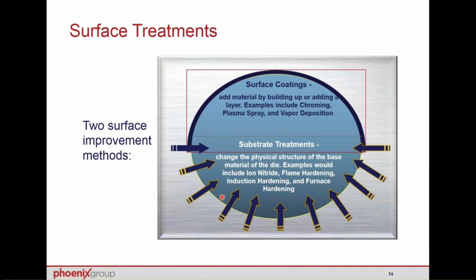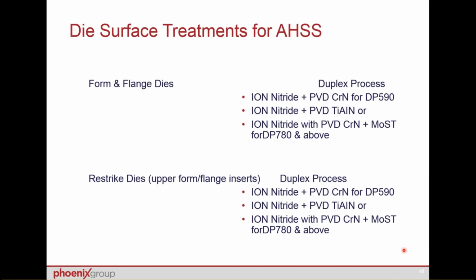With the ion nitriding, because you have to slowly bring it up to temperature, hold it for a period of time in the oven to allow the penetration of the nitrogen ions, and then slowly cool it back down so we don't end up with thermal fracturing or warping, it might be a 3 or 4 day process in order to get a die back. Also, you have their equipment tied up for a longer period of time. So ion nitriding, although it is more durable, is also more cost prohibitive. It's probably 2 to 3 times the cost of chroming a die, but it definitely does give you a very long-lasting, durable finish also. These are chroming alternatives.